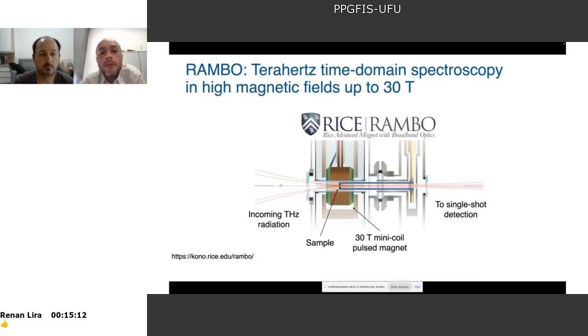Okay, for the experiment with magnetic field, we use very, very high fields up to 30 Tesla in a special setup called Rambo. And Rambo means Rice Advanced Magnet with Broadband Optics. So in this case, there is here a pulsed magnetic field. It's not possible to have a constant 30 Tesla, only pulsed. And here there is a cryostat. In this cryostat, we have this tube, and the sample is connected to the cryostat, but fixed here in the center of the coil.